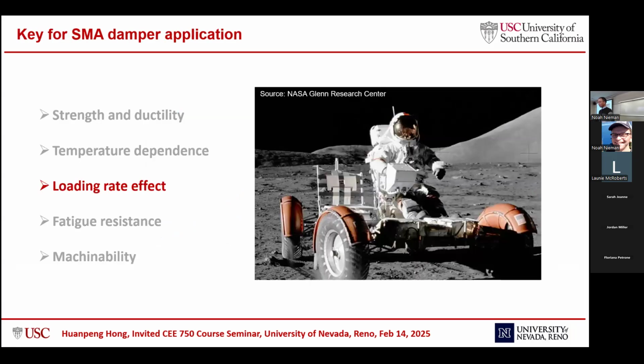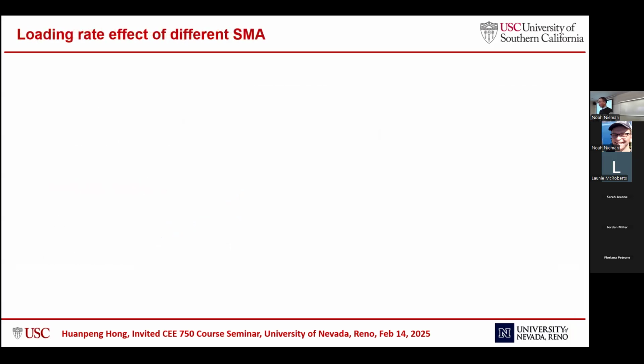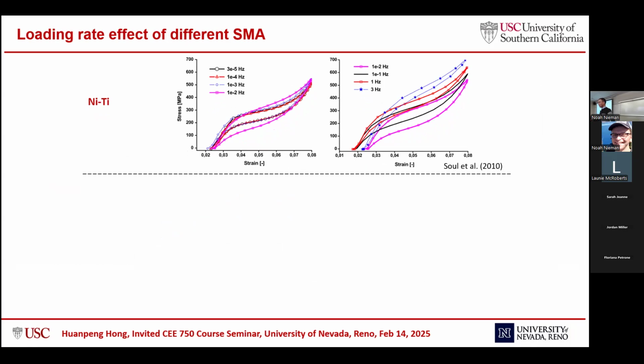So next, I'll briefly introduce the loading rate effect. For seismic application or some other types of vibration control, the loading rate might be an important factor. Nickel titanium alloy is sensitive to loading rate because a high loading rate generates an adiabatic condition, so the temperature inside the material will rise. The hysteresis loop narrows down, and the yield stress increases a little bit.